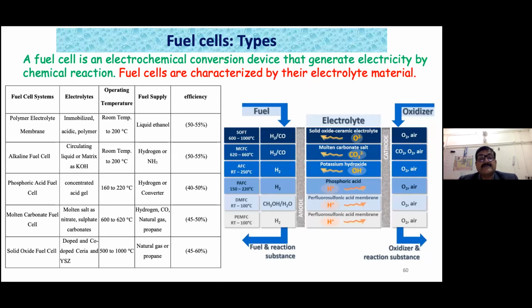So these are different types of fuel cells. They are basically polymer electrolyte membrane fuel cell, alkaline fuel cell, phosphoric acid fuel cell, molten carbonate fuel cell, and solid oxide fuel cell. These cells are named based on the electrolyte material which you are using. For example, in the polymer electrolyte membrane fuel cell, you use immobilized acidic polymers as an electrolyte. For example, in the solid oxide fuel cell, you use doped and co-doped ceria and yttria stabilized zirconia. So different electrolytes you are using, and then there is the operating temperature.